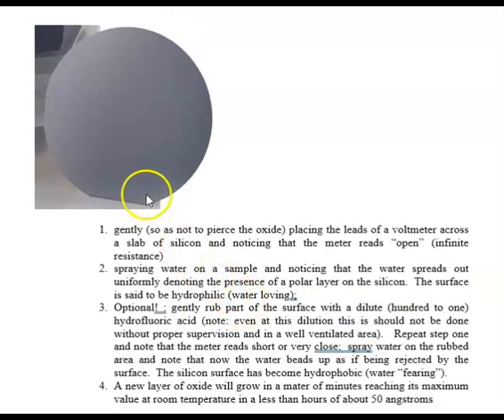But what I do is I take a Q-tip and take part of the wafer, say this part over here, and I rub HF over this part of the wafer, basically dissolving the glass. And then I spray water, and I notice that where I have the glass, we get a nice smoothing out of the water. It spreads out very nicely. But where we have the silicon, it is hydrophobic, so the water beads up. And that is a very graphic way to show that we do have a SiO2 layer on the silicon, because when we get rid of it, we don't have it.